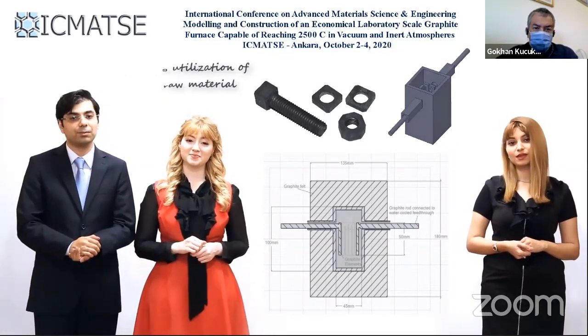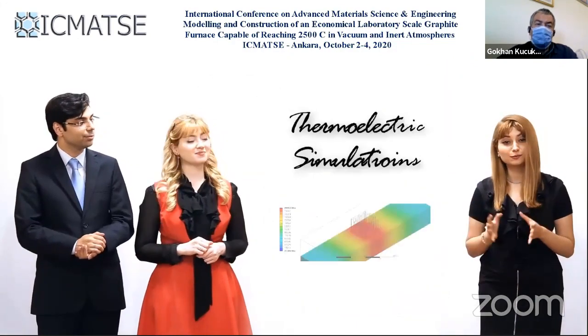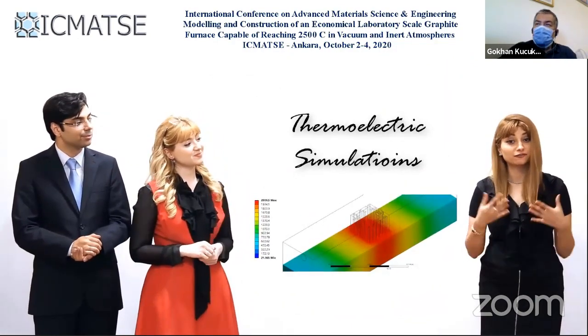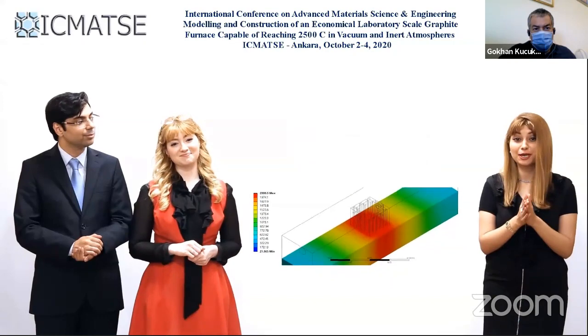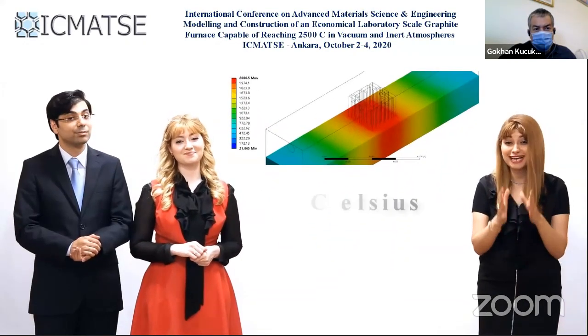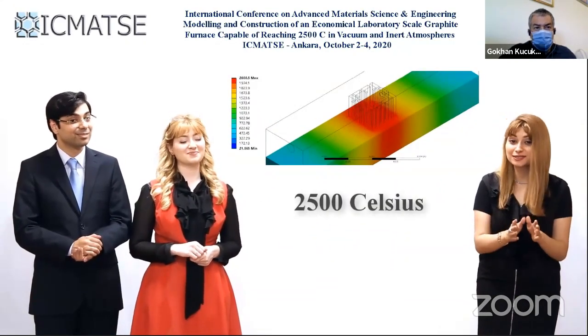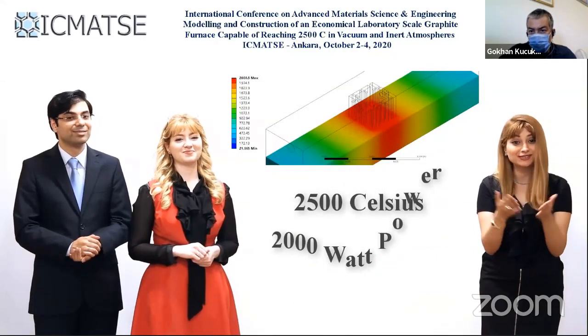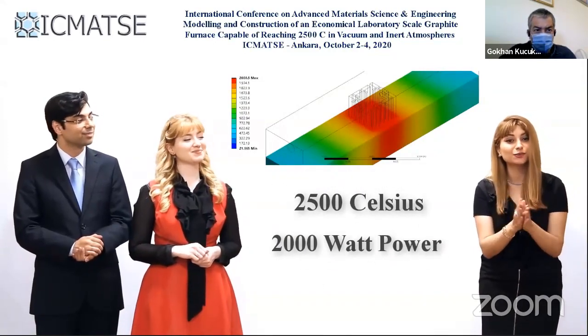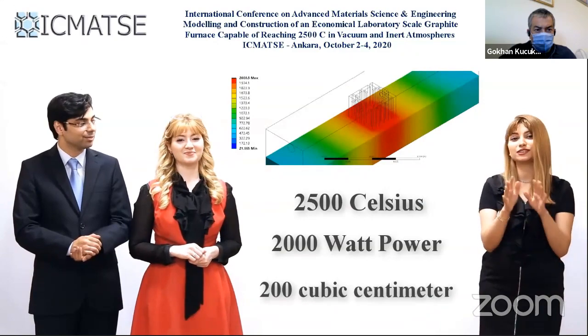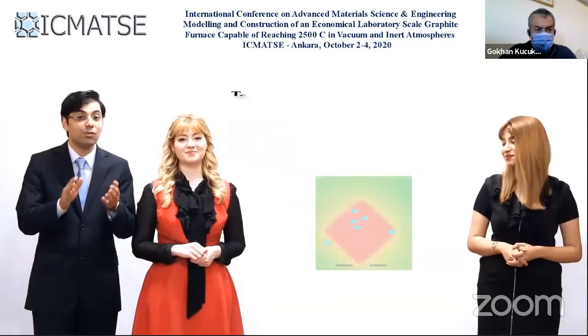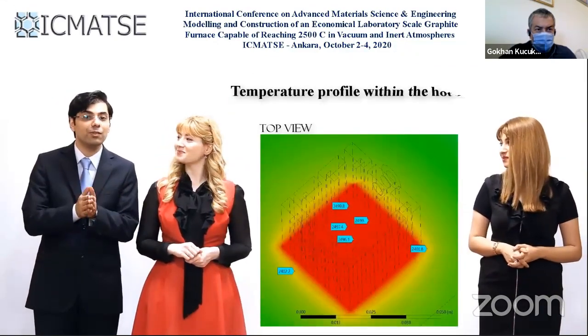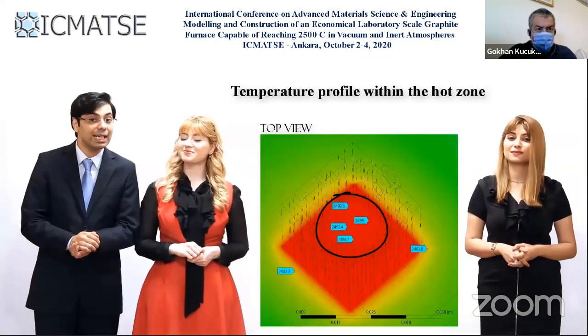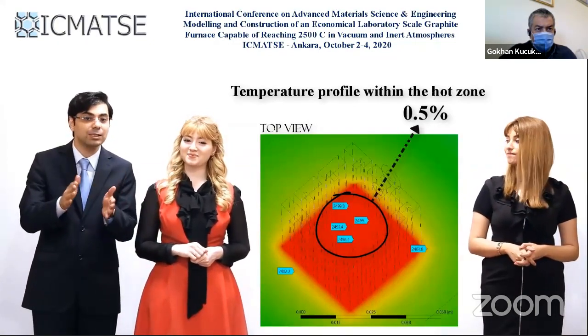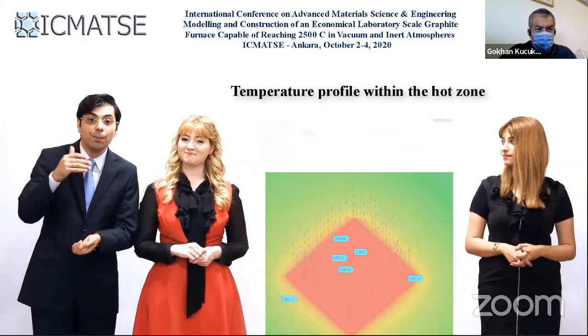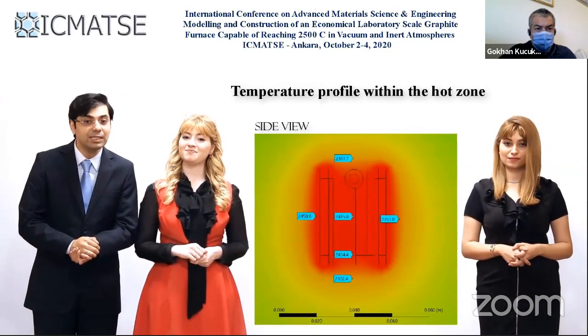Our thermoelectrical simulations on various graphite grades have shown that it is possible to achieve a temperature of 2,500 degrees Celsius with an approximate power of just 2,000 watts for a usable hot zone volume of approximately 200 cubic centimeters. Furthermore, the temperature variations within the central 60 cubic centimeter of the hot zone do not exceed 0.5% of the maximum furnace temperature. The mentioned values have been repeatedly confirmed experimentally.